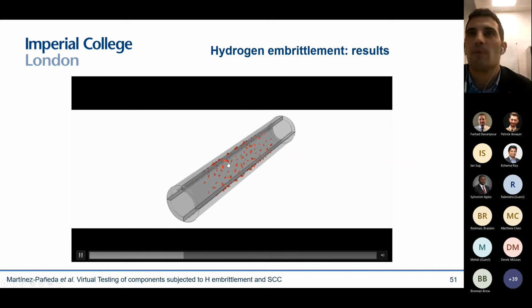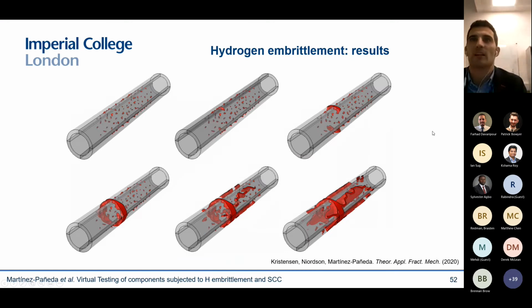You can see here at the top that when I load to the in-service conditions, some of these pits start nucleating, growing, and coalescing with each other. And eventually you get coalescence of multiple pits and complete failure of the pipeline. You can see it here.